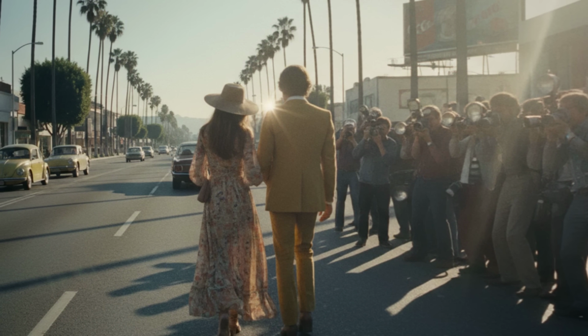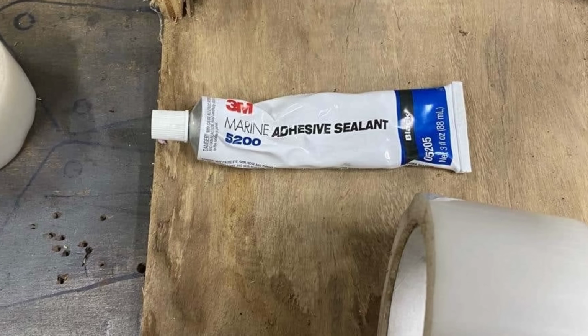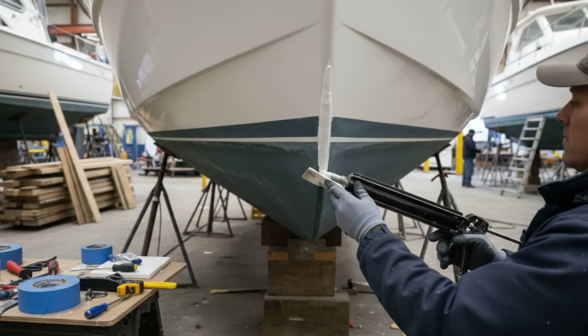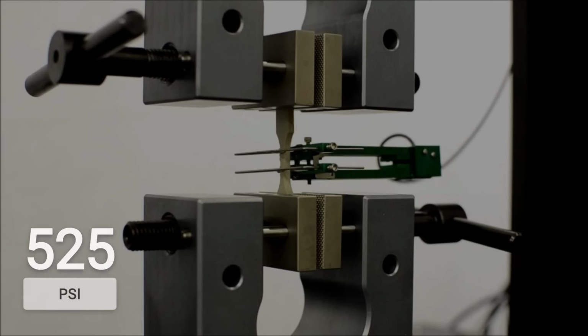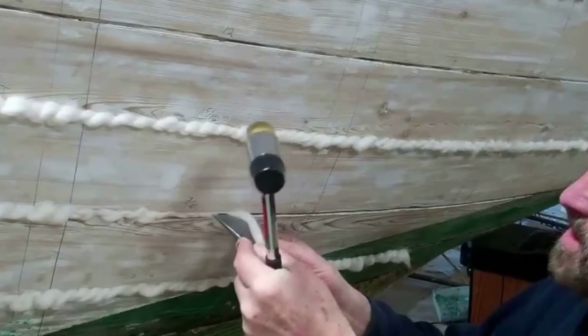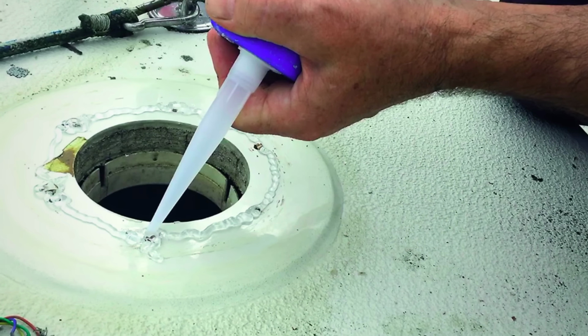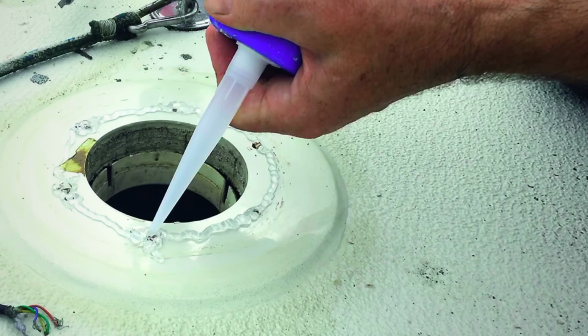On the other end are the modern marine adhesives, each defined by their chemical class. 3M 5200 stands out, a moisture-curing polyurethane designed for structural bonding. It cures into a permanent, elastomeric joint with a tensile strength of about 700 pounds per square inch. That figure means you are not just sealing, you are fusing materials together. 3M 5200 is what you reach for when you need a hull-to-deck joint to survive a hurricane or a crane drop. It was never meant for hardware you might want to remove later. Using it for a cleat is like lighting a match with a blowtorch, overkill and often regrettable.